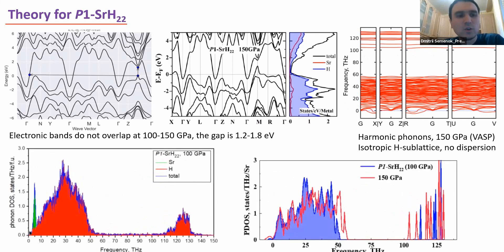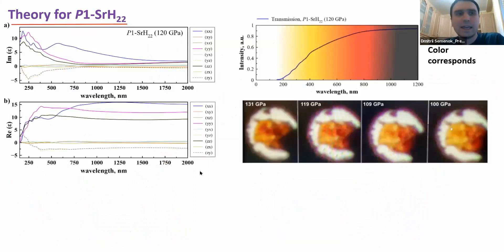Including anharmonic effects, inclusion of anharmonic effects stabilizes the structure almost without structural changes. Because we know the structure, we can calculate also the dielectric function and compare the transmission, predicted transmission spectra with real color that we observe. You can see that this curve is a theoretical curve of transmission. We see that the compound should transmit mostly yellow or orange and red light, so it should have a visible color bright yellow or dark orange as shown in this slide, which is in very good agreement with experimental observations again.